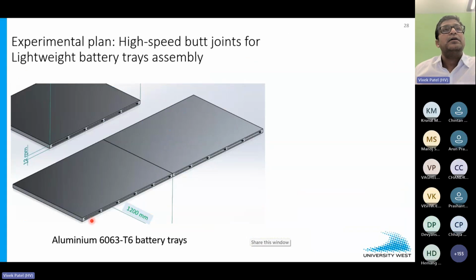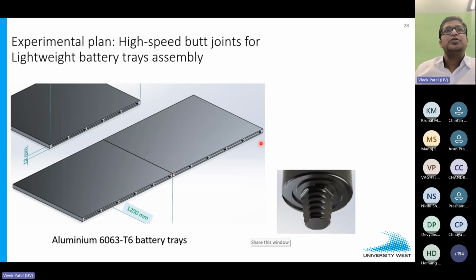And this is how the floor panel looks. These are nothing but the extrusion floor panels for cooling of battery cells, and you need to weld them as a butt joint when it comes to the assembly. In that process, we worked on a different tool design so that the tool can work at high welding speed, 5 meters per minute. Because for high speed friction stir welding, the main challenge is that the tool should survive. There is a high chance that the probe, the smaller diameter, can break from the shoulder, the bigger diameter.